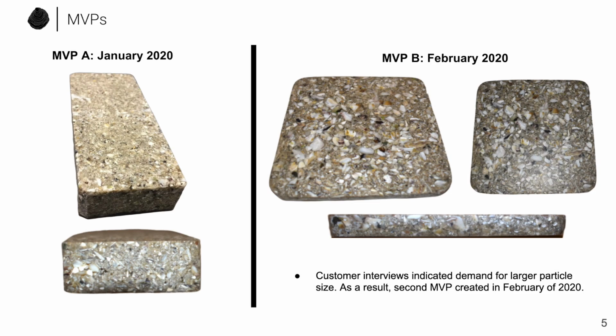Our initial MVP, made in January of 2020, seen on the left, consisted of roughly 30% resin by weight and was made with the smallest particle size available, less than 3.35 millimeters, and had a density of roughly 2.1 grams per cubic centimeter. This MVP was made quickly to showcase our technology at a business competition, where we received valuable feedback from customers demanding larger particle size in the sample.